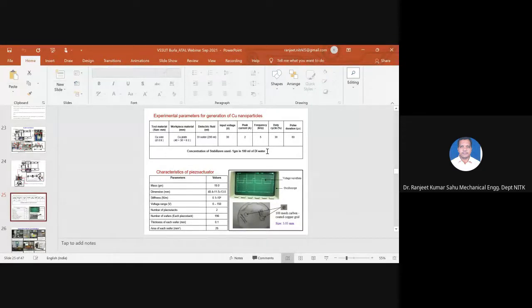Those debris which are dispersed in the dielectric fluid, we can call colloidal debris. We collected them in a glass vial or glass tube. Then we went for certain characterization studies. After collecting the debris dispersed in the dielectric fluid from the glass vials, we dribbled 3 or 4 drops on carbon-coated copper grids. Then we allowed them to dry for 2 hours. Whatever precipitate remains on the grid, we took for transmission electron microscopy study. In that study, we will ascertain the size, shape, and distribution of the particles. Then further, we went for certain application studies also.